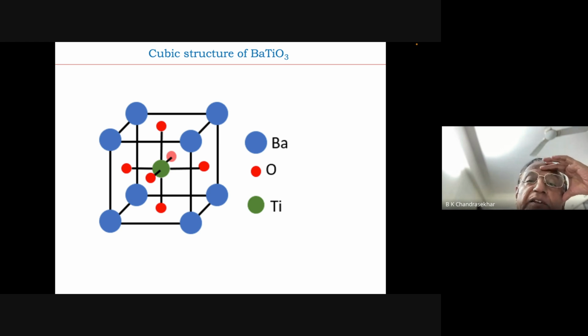And that deteriorates the electromagnetic properties of this material. As I said, in the 70s hundreds of laboratories used to work on this material to develop a superior version. Now with microwave, they are able to achieve the required tetragonal phase even at 700 degrees centigrade very easily, in less than 15 minutes. What used to take 2-3 hours of soaking time at 1300 degrees centigrade can be done in 15 minutes at 700 degrees centigrade, because the titanium present interacts with the microwave very easily, and therefore the rate of reaction dramatically accelerates, forming the required tetragonal phase of barium titanate.